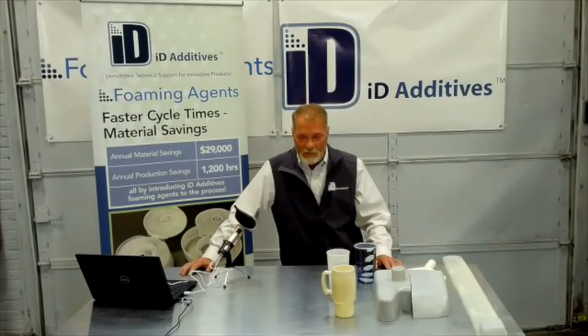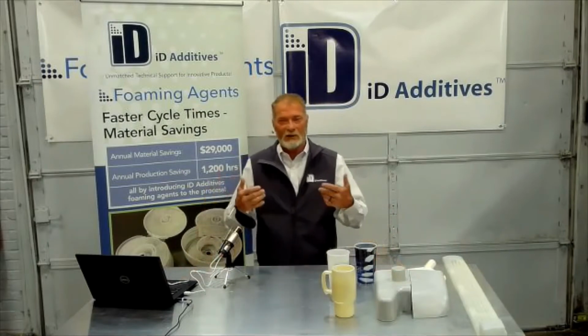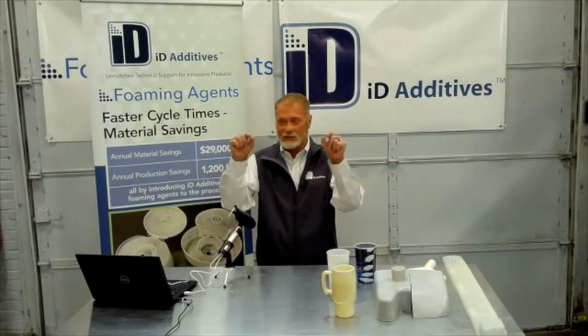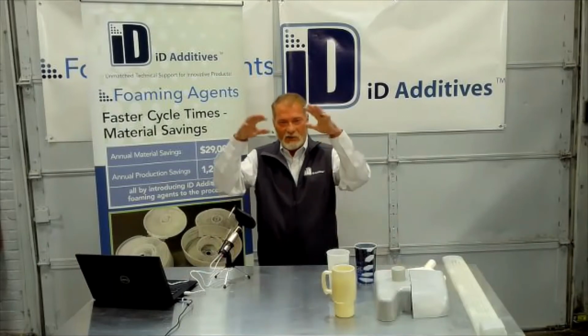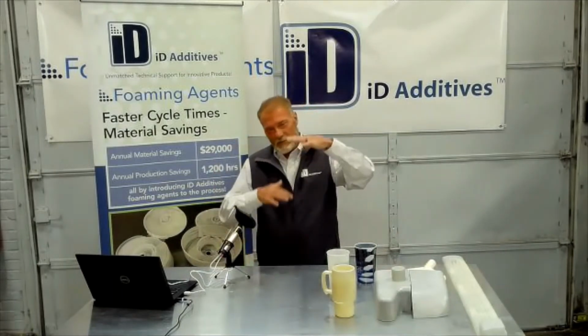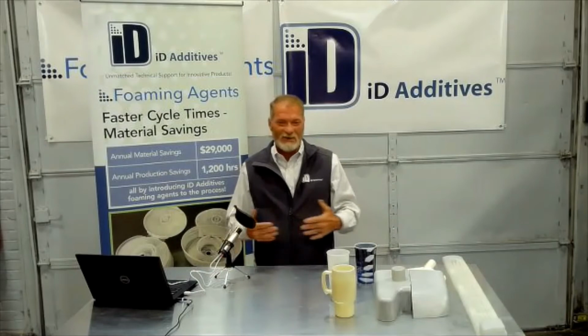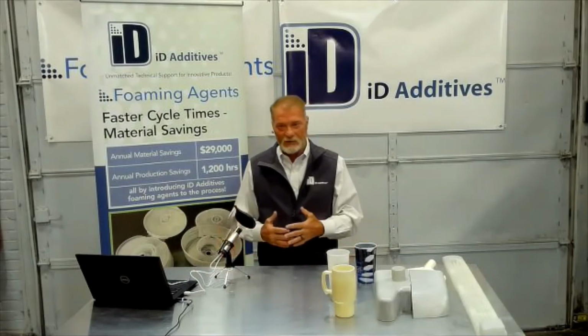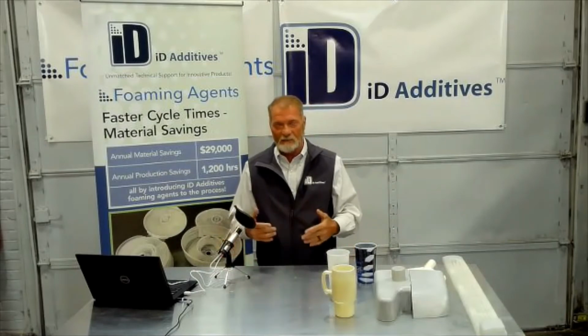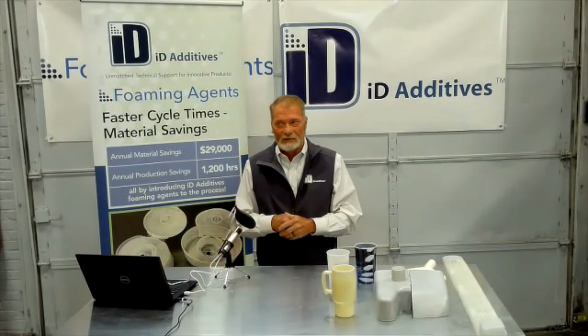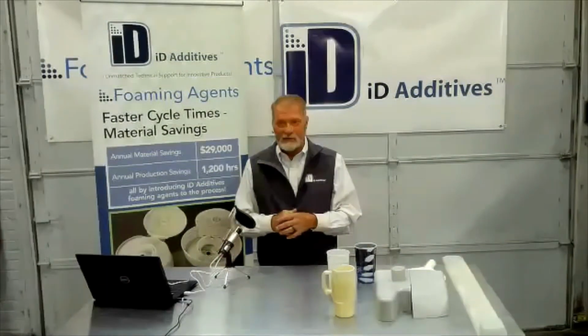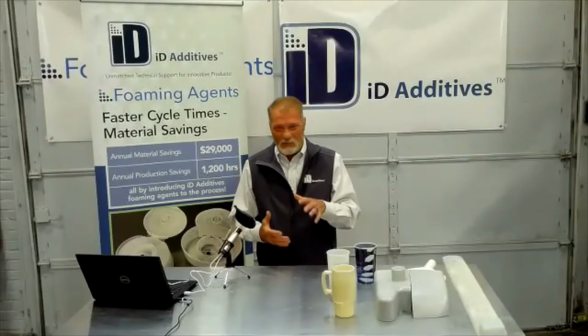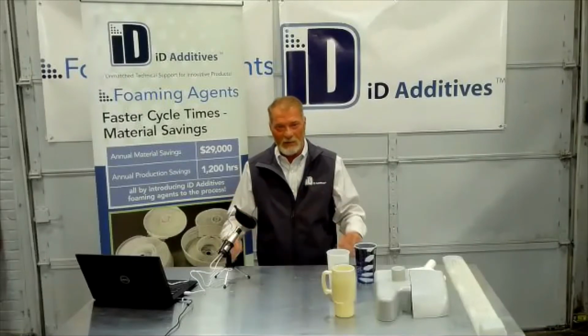On thermoforming and sheet, the draw length is important because now you've got a cell structure in the wall, right? And then you're going to stretch that. And the further you stretch it, the tougher it gets. So if you're doing fairly short, I'm saying probably anywhere from 6 to 8 inch draw, somewhere in there, maybe even shorter. The shorter the draw, the better it is.